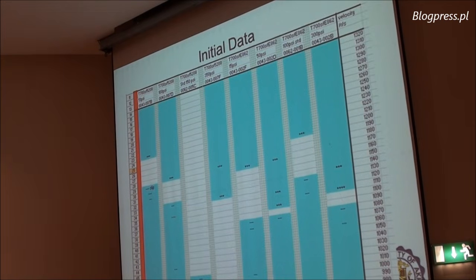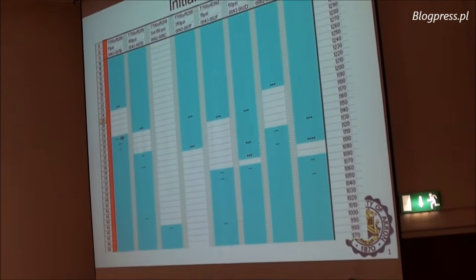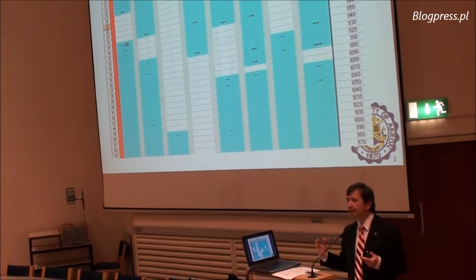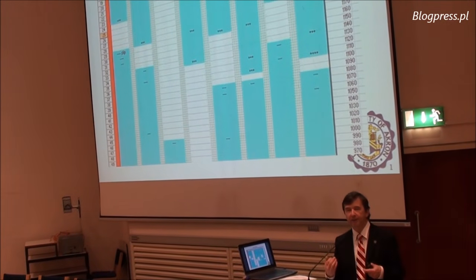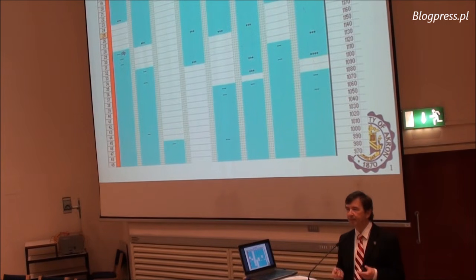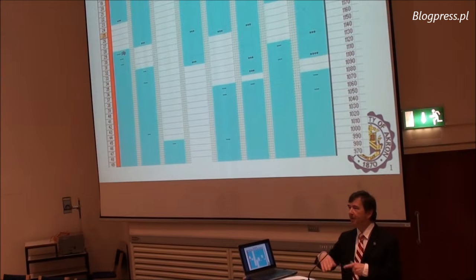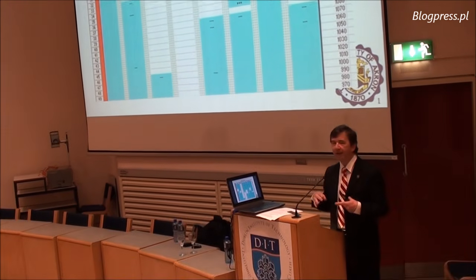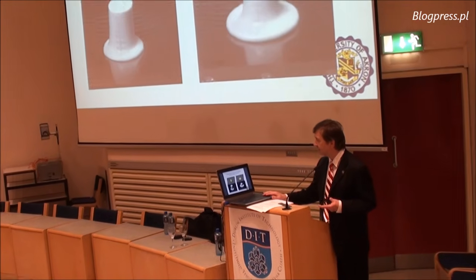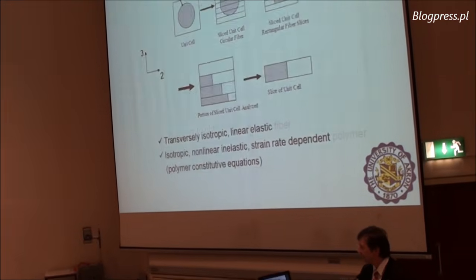You have here the whole matrix of damage, and you can see that for the same fiber, just by changing the matrix, the so-called V50, which is the velocity of penetration, can be significantly different due to the fact of interface strength. In fact, again, the common sense would tell us that the stronger interface, the better. In fact, in the impact, the weaker interface, the better, because the material starts to spread the forces through itself by decomposing itself, and fibers pulling from the matrix and from the other fibers can absorb much more energy, therefore it can get much safer for the experiment that we use.